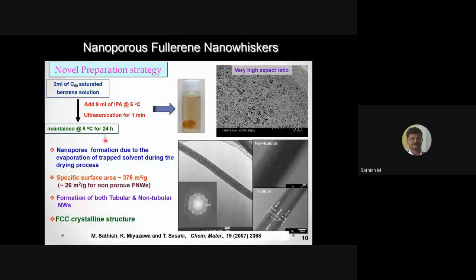Generally, fullerene nanowhiskers are prepared using toluene and isopropyl alcohol instead of benzene. In such a case, I get this kind of rods, but without this porosity. I showed you some porosity; those pores are optional. We generally call those fullerene nanowhiskers, but what we are talking about here is nanoporous fullerene nanowhiskers. You can see the difference. Plain fullerene nanowhiskers have 26 meters squared per gram, whereas nanoporous fullerene nanowhiskers have 376 meters squared per gram. As I told you, you can have both tubular and non-tubular.